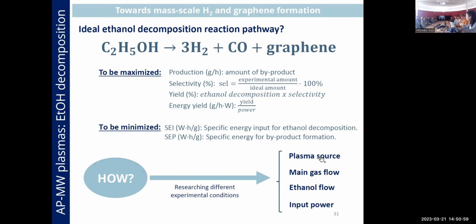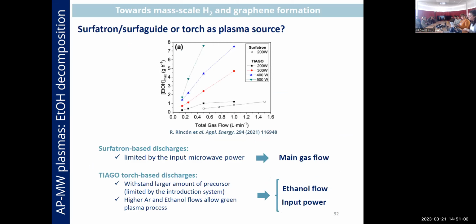Well, playing with the plasma source, the main gas flow, the ethanol flow, and the input power. So first of all, we checked with our 2 systems, Surfatron and TIAGO torch, the maximum amount of ethanol that can be introduced. I mean, if we introduce a higher amount of ethanol, it is supposed to have much more hydrogen and graphene being formed. So this is something that we checked. Here you have the maximum ethanol amount that can be introduced in our system, considering different argon gas flows. Remember, I said that our Surfatron device is limited in power. So our device cannot work with powers higher than 200 watts, in contrast to the torch, which can work with higher powers.